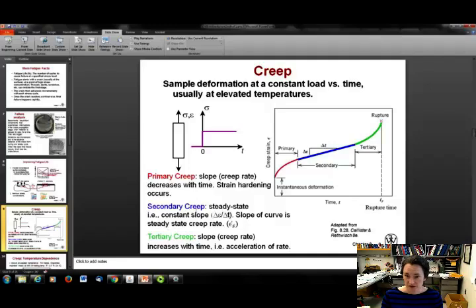The slope of that, here we're plotting creep strain versus time of service, okay? So the slope of this secondary curve is really important because the part spends most of its life in that secondary time frame. It spends most of that time in the secondary stage. The primary stage doesn't take very long, and neither does the tertiary, maybe just a few days for each of them. The secondary strain rate curve can last for years. So that slope right there is very important, and we'll talk more about that. And then finally, it exits the secondary creep and enters the tertiary creep phase, and then the slope actually increases with time until the part finally ruptures. So you want to stay away from that.